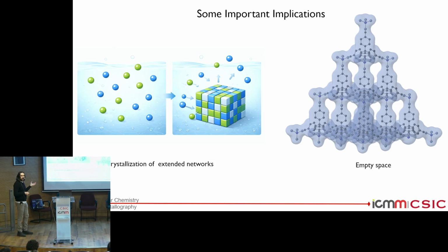And on the other hand, you are doing the crystallization at the same time that you do the chemical reaction between the different components. So you have to choose the right conditions for this to happen. Another important implication is about porosity. It was already noticed that this type of material has a lot of empty space inside. When you have these networks, inevitably you will have empty space that is not occupied by the molecules that are building the framework. Now, in the case of Robson's compound, they were filled with counteranions. The ligands that he used were neutral. So when you are using metal atoms, then you will have counteranions in the pores, and they cannot be removed. And also there are solvent molecules inside. The strength of the bonds in these coordination compounds was okay, but it's not too high.